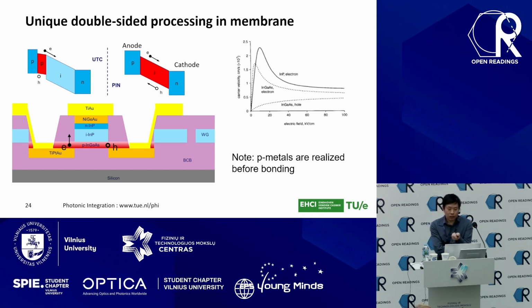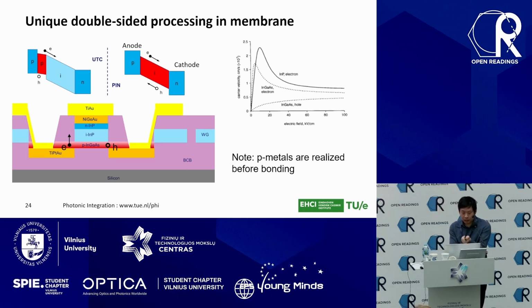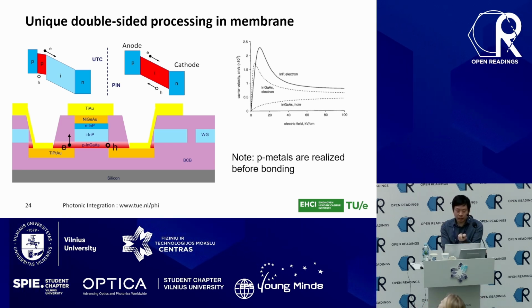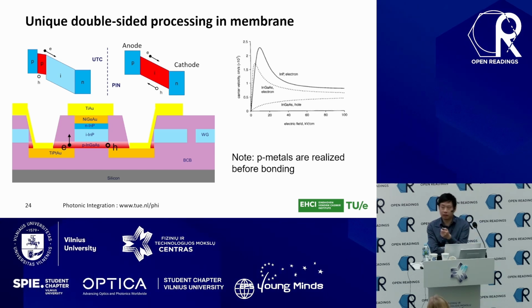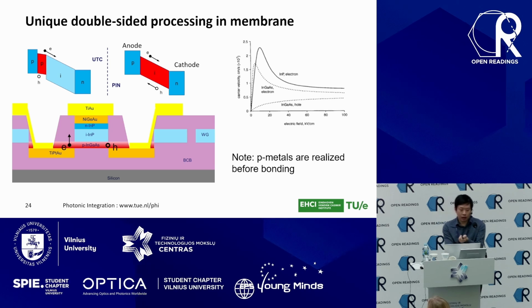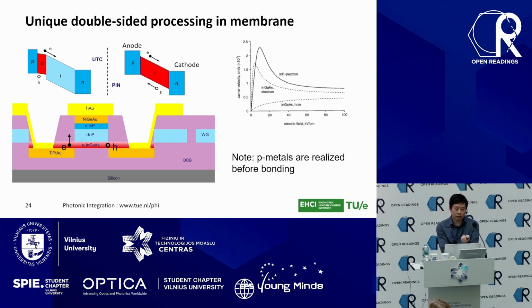And if you see the diagram on the right, you see that the limitation here is that electrons travel much faster than the holes. Holes are heavy. And those holes, their travel time becomes your major bottleneck in these typical photodiodes. So people designed a new device called the uni-traveling carrier, UTC, where the absorption region, if you look at the left side, is not in the center anymore.